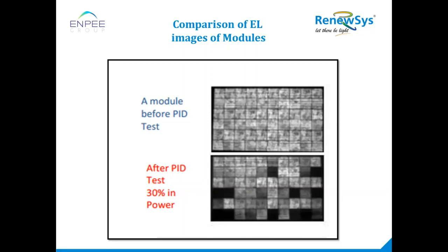So we have another question that has come in with regards to the encapsulant again. Will increasing the thickness of the encapsulant reduce the PID effect? Yes, it will decrease the effect of PID, but at the same time, it might not be a viable option in the solar industry, because increasing thickness is protective in terms of PID, but at the same time, it is going to decrease the transmittivity of the light.